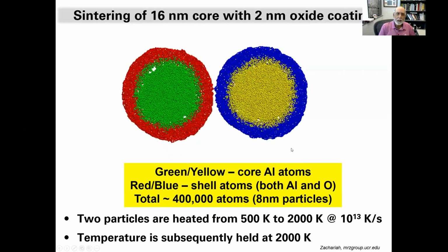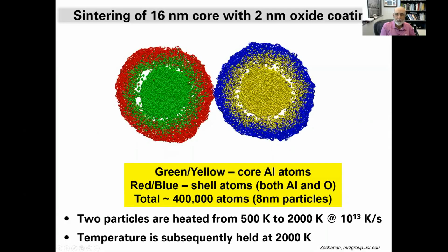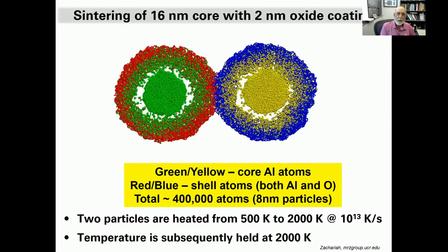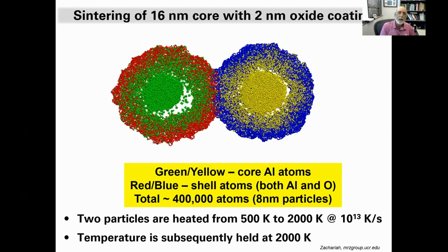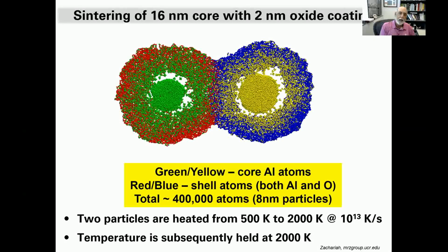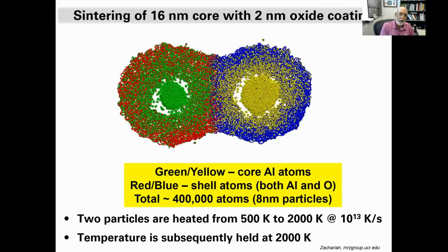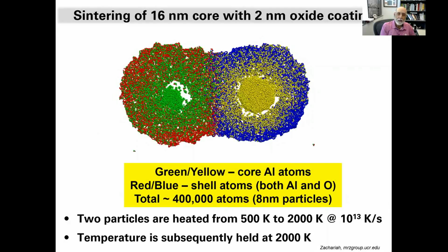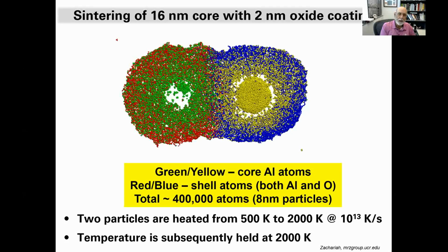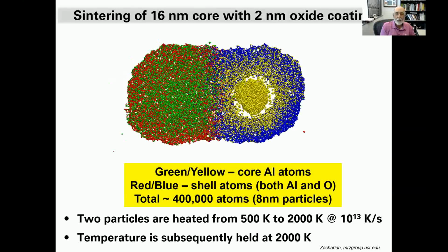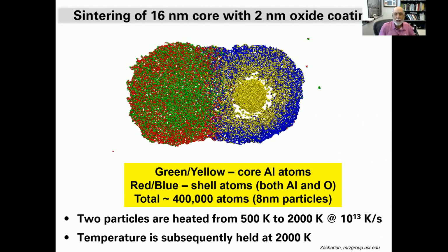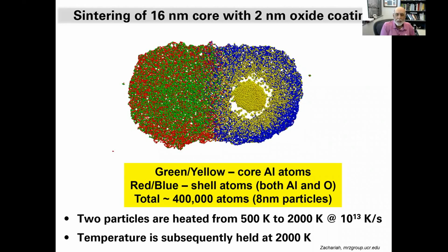So if you look at two aluminum particles, this is a molecular dynamics simulation with its oxide shell around there, and just heat them up, you start to see them coalescing together. And they coalesce at a temperature much lower than what you would expect. Now, why is that when you have this oxide layer around there? The reason is the moment oxygen diffuses into that, aluminum diffuses into the oxide layer, it's not aluminum oxide anymore. It's something a lot softer.